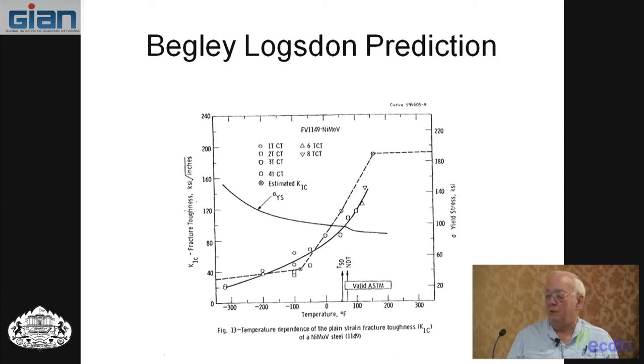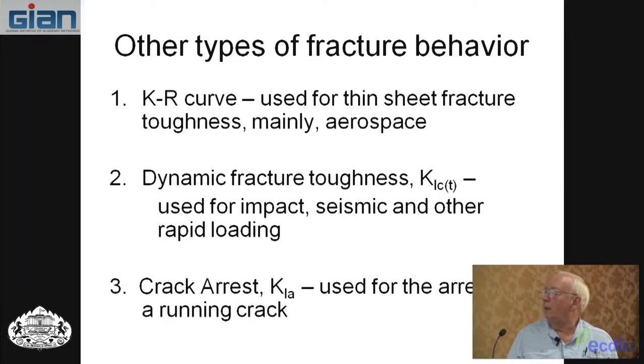This Charpy correlation was something that people were looking for because, one, it was easy, and it worked pretty well if you stayed within your class of materials. You couldn't take that method and generalize it. For example, it wouldn't work at all with nonmetals or non-ferrous metals. It had to be steel. Number two, you had to stick to your own class, like a yield strength of about 100 KSI yield, whatever. So it's okay, but it's not real great.